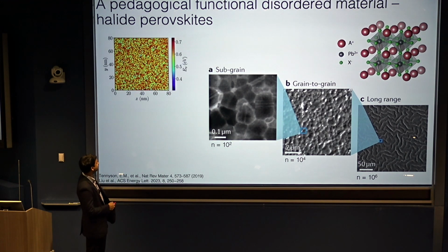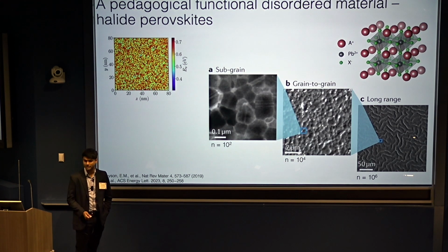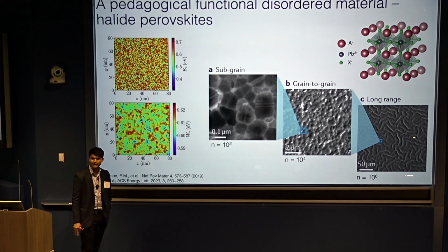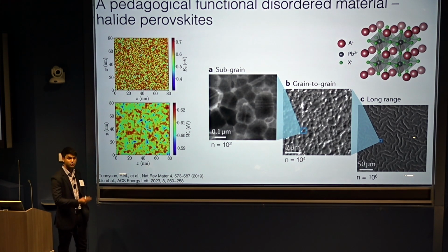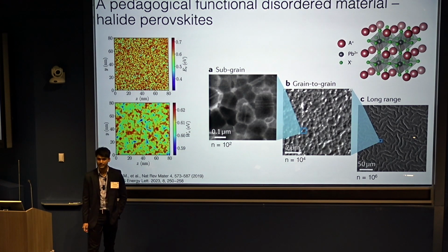And as part of this grant, Richard and Yun Liu, a collaborator of mine, and Marcel have investigated what actually happens on even shorter length scales, where you allow this halide site over here to vary as a function of space, which varies the valence band energy. And what they discovered through the landscape was essentially the high kinetic energy of the electrons in these systems pretty much washes out these potential fluctuations, giving us a pretty nice insight into why carriers can move so far and so efficiently in this really disordered class of semiconductor materials.